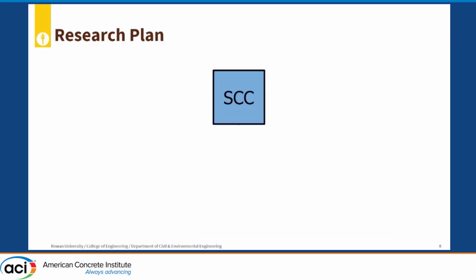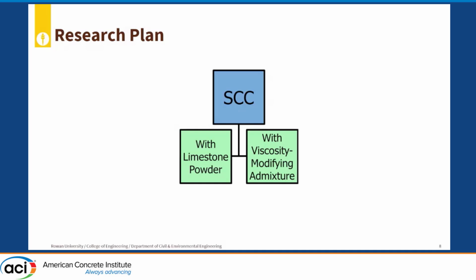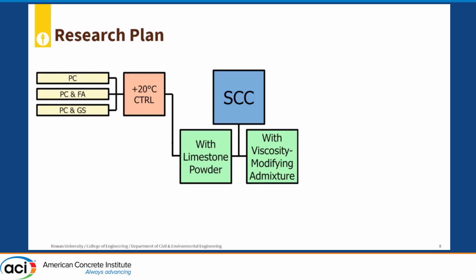We classified our SCC into two according to the type of viscosity modifier used. One uses limestone powder, and the other uses viscosity modifying admixture. For every classification, we have three types that differ in mixing and casting and curing temperature, as well as some admixtures used. The first one is mixed and cured at 20 degrees Celsius. We call this our control mixture. For every type, we have three subtypes that differ on the cementitious materials used. The first one has 100% Portland cement. The second has 25% fly ash and 75% Portland cement. And the third one has 25% slag and 75% Portland cement.